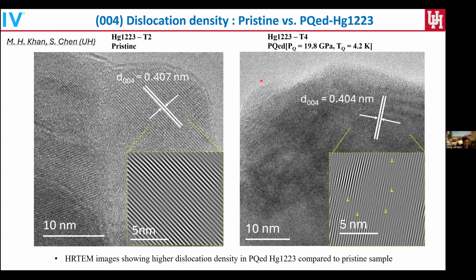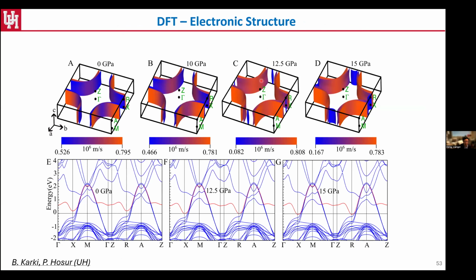In an extreme case, it could even be a factor that's not in favor of TC enhancement, but now plays an important role to retain this structure-wise or property-wise that favors higher TC. So that's why we come into these defects. We're trying to look into more experimental evidence.